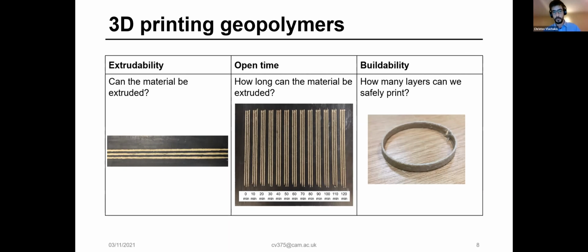So in this situation, we were able to extrude the material for 120 minutes, so 2 hours, at a reasonable consistency. And we're able to print it for 10 layers without any noticeable deformation. So that was actually quite a bit higher than the requirements of this study.